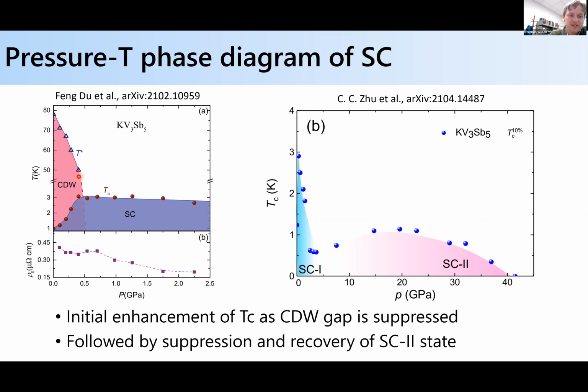And then after the CDW is completely suppressed, they see this large flat region where the superconductivity doesn't care much as you go up to 2.5 GPa. And this is more or less consistent with a conventional picture of closing the charge density wave gap and then providing more density of states for your superconducting state, and then you can have a higher TC. So that's kind of a conventional picture.